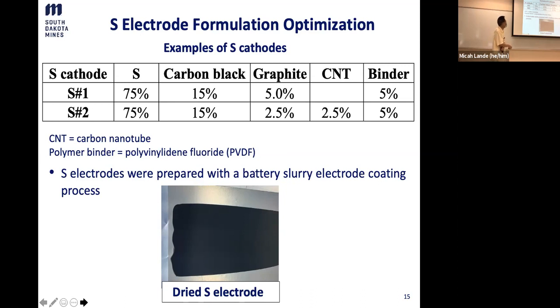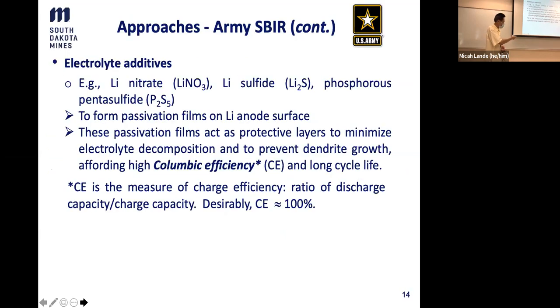Yes, a good question. So when you add this additive, you want to take advantage of carbon nanotube. In terms of carbon nanotube, it's longitudinal, one-dimensional, and it provides a good conductive pathway, but also it is expensive. So you try to minimize that, and also we found out that adding more doesn't mean the same proportional increase of the conductivity or performance. So there's some amount that is just enough. So that's the reason for the amount of